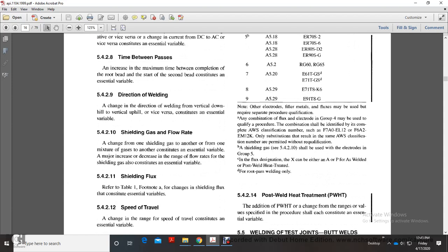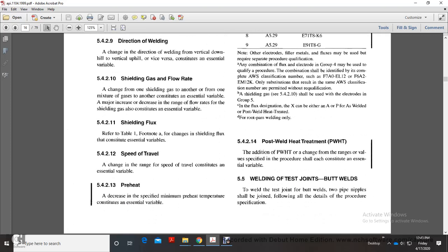5.4.2.10 Shielding gas and flow rate. A change from one shielding gas to another, or from one mixture of gas to another, constitutes an essential variable. An increase or decrease in the range of flow rates for the shielding gas also constitutes an essential variable. 5.4.2.11 Shielding flux. Refer to Table 1 footnote. A change of the shielding flux constitutes an essential variable. 5.4.2.12 Speed of travel. A change of the range of speed of travel constitutes an essential variable.